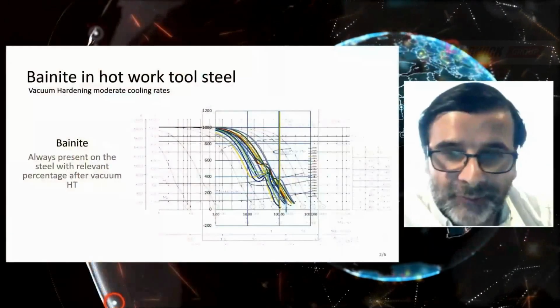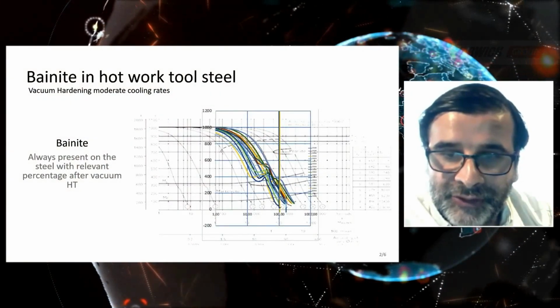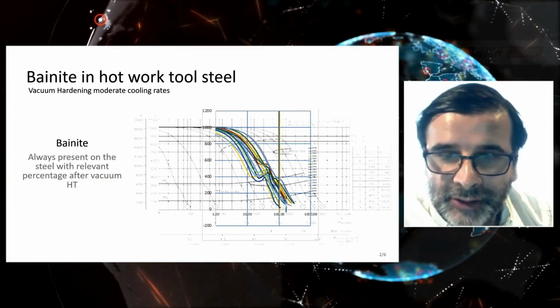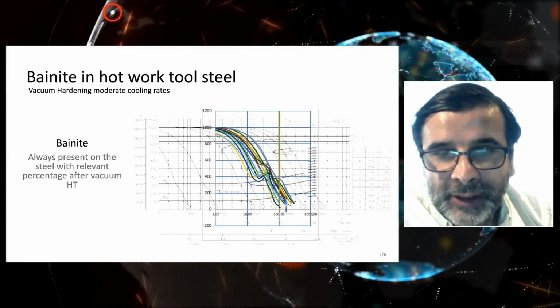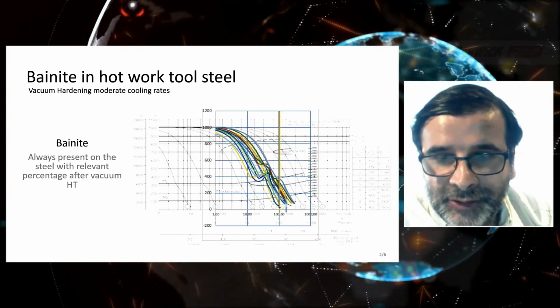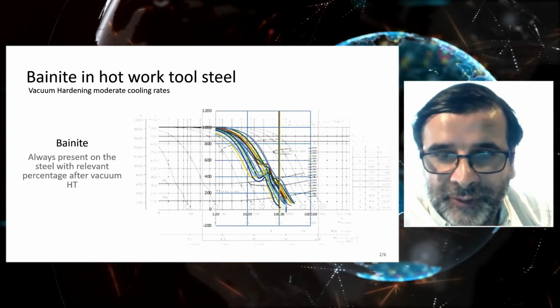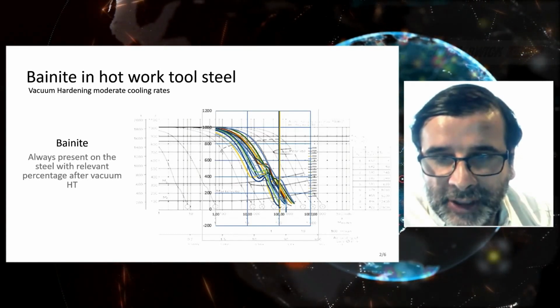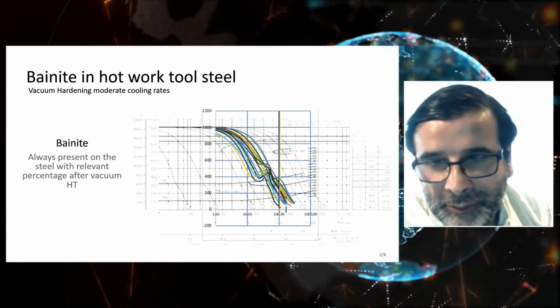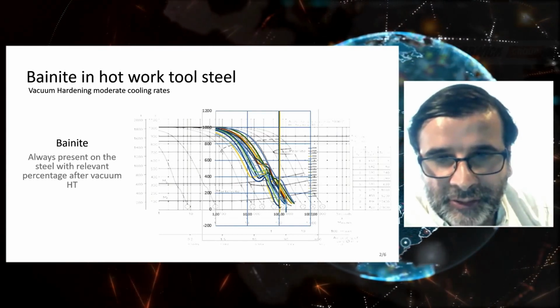Okay. Can you comment, because now we have something about also bainitic microstructure, and we made a short discussion before our official discussion today. Can you comment on the next slide that you prepared before? Yes, what we measured was real hardening cycles, real loads, real parts, and we measured the cooling speeds reached for die casting applications from smaller to larger tools, and this is the result that we achieved.